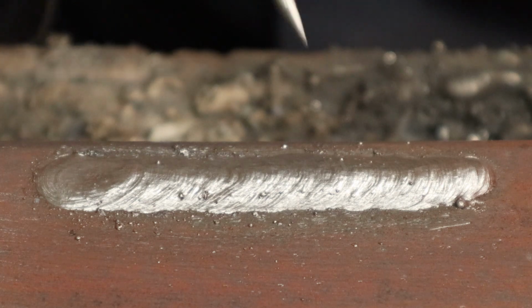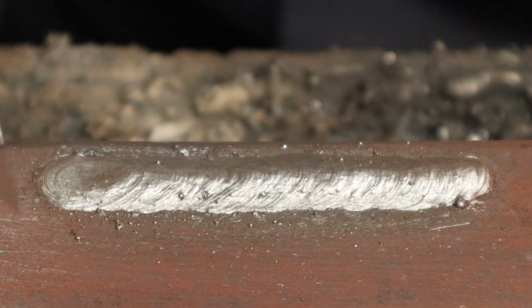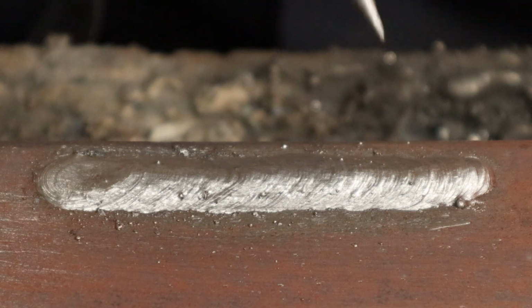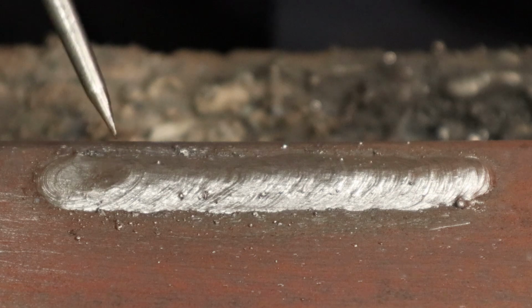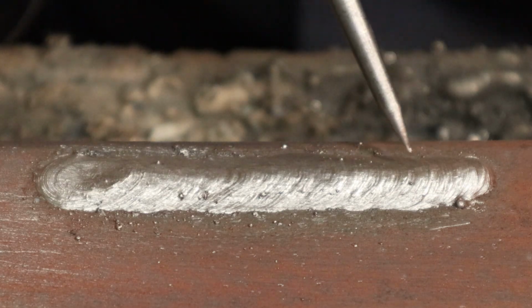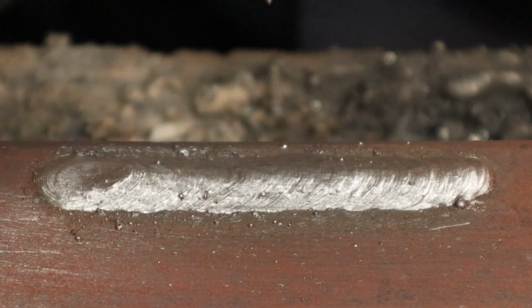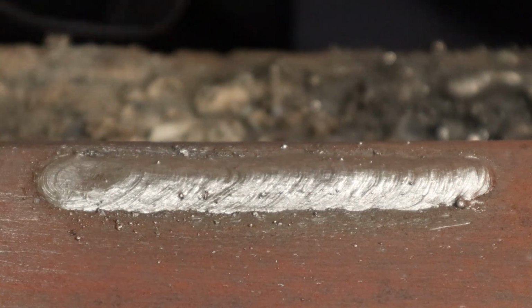So as you are dumping heat into the material, it's going to start acting like it's a hotter weld bead because the material itself is getting hotter as well. Now, there isn't a lot of spatter on here, so I must have been able to maintain that 1/8 of an inch gap as I went along by constantly feeding the electrode in as I was moving.